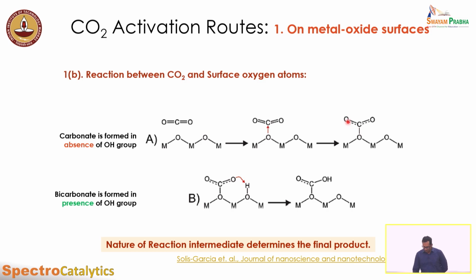But now, if we have a significant amount of OH groups present on the same metal oxide, then instead of a carbonate, the oxygen of the carbonate will attack the hydrogen of that OH group, and now we have a bicarbonate type of species present. So that's how having an OH group on the surface versus no OH group leads to a different reaction intermediate.